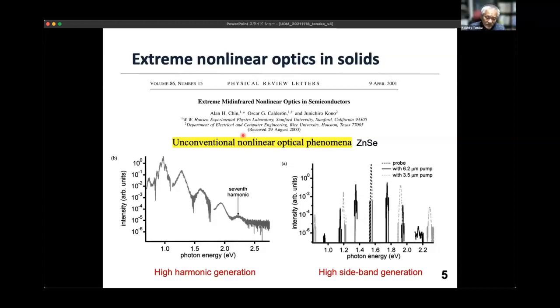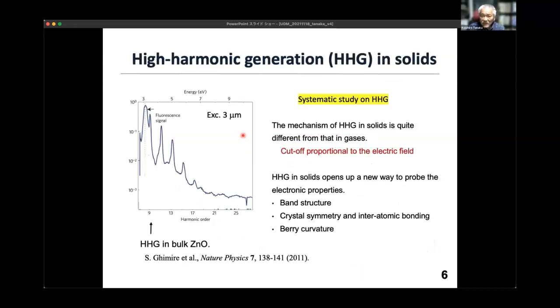After 10 years from 2001, the Stanford group showed very beautiful high harmonic generation from zinc oxide. This is a typical result. They also used a 3-micron mid-infrared laser and did a systematic study on high harmonic generation. They showed that the mechanism of high harmonic generation in solids is quite different from that in gases. For example, the cutoff energy, which is a beautiful observation in atomic systems, is in solids proportional to the electric field. This is quite different from the atomic system.